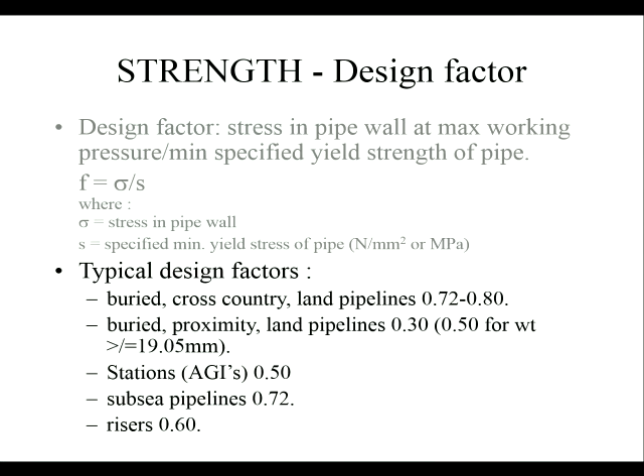At stations, that's things where people might go but don't usually go, so pumping stations, pig traps, compressors, all of those sorts of things, we might have a higher safety factor than the minimum because people go there, but we don't go right down to the lowest. Subsea pipelines, because of the external pressure, they're actually a lot safer intrinsically. So we operate closer to the yield stress, and the safety limit goes up. The exception being on risers, because a riser might come up in close proximity to workers, so we would tend to use a slightly lower design factor. And you can argue that these are safety factors. The lower this value is, the more safe you're trying to operate.